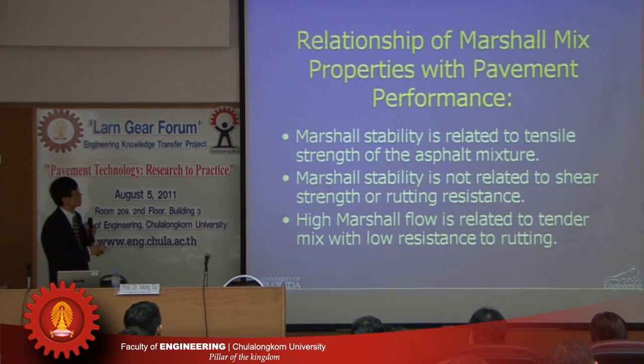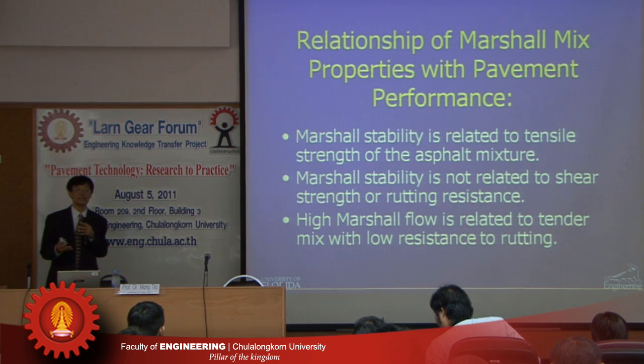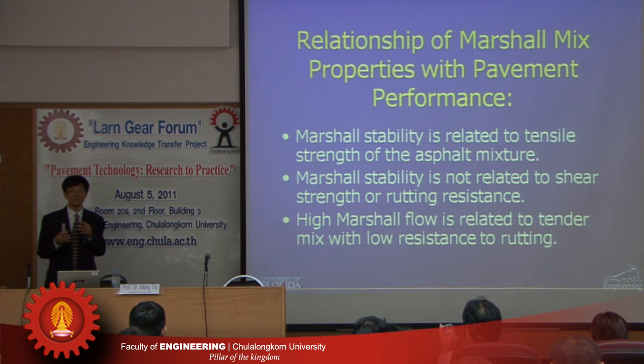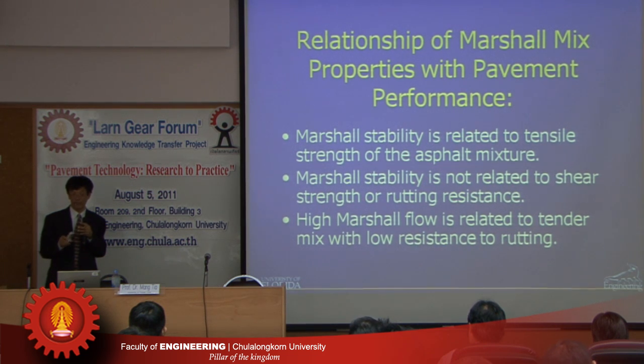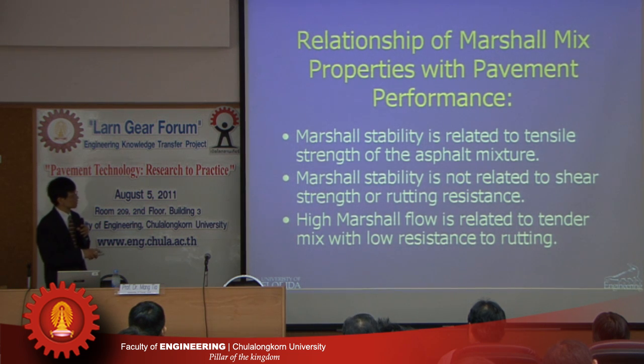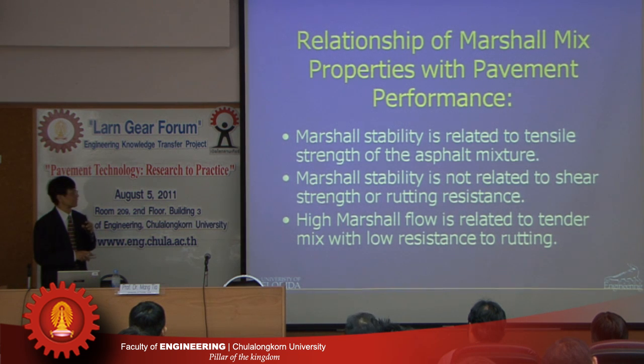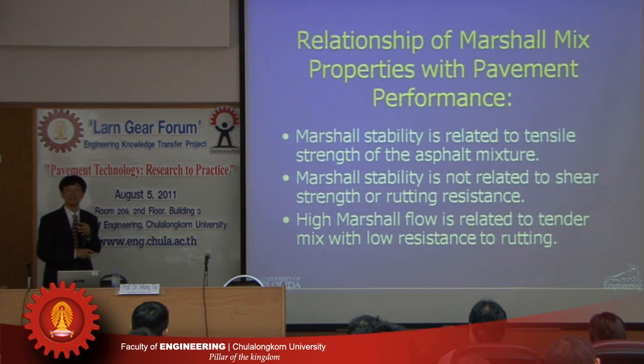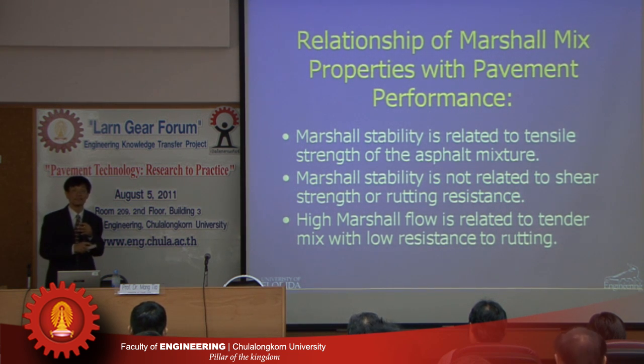Marshall Stability is not related to shear strength, so it's not related to rutting resistance. If you try to increase the rutting resistance by increasing the Marshall Stability, it doesn't help, because it's not related to shear strength, which is related to rutting resistance. What might be related to rutting resistance is the Marshall flow. We try to keep the Marshall flow not too high. A high Marshall flow is related to a tender mix with low resistance to rutting. So there are some merits in the Marshall Mix Design method, but there are some possible problems as pointed out.